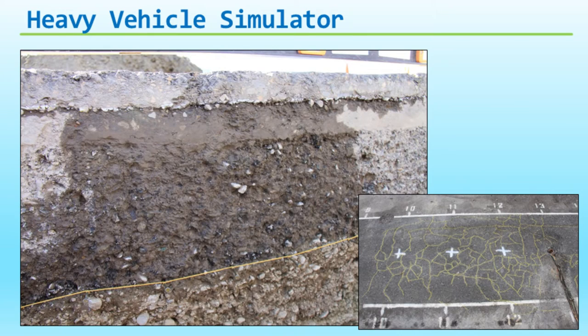So we opened it up, and we had pumped a lot of water into this layer. It was really a worst case scenario with water. And again, this is the asphalt surfacing over here. Basically we got a debond between the asphalt and the recycled layer. So the asphalt was working independently of the supporting layers underneath that. It did fatigue crack because the asphalt failed.